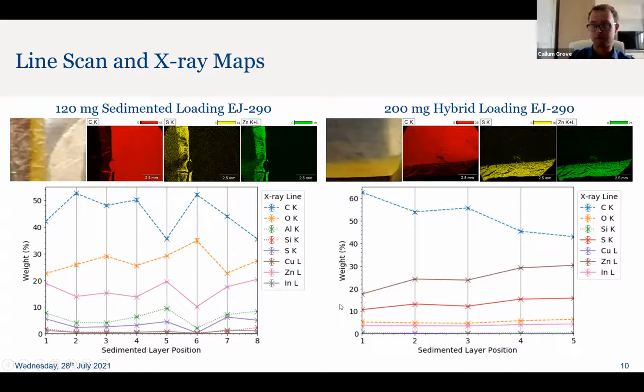So as I said, that was an average across the sample, and then this is a line scan across the sample. So there's a significant amount of deviation as we go across the sample for the sedimented loading sample, and you can see this in X-ray maps as well. That's because we developed cracks in the sedimented layer from when it was cut off the side of the sample, and in these cracks, there was a high amount of carbon forming, which produces these erroneously high carbon contents, because we coated our samples with carbon to produce better conduction. Compared to the hybrid loaded sample, we don't see those cracks as significantly in the X-ray maps.